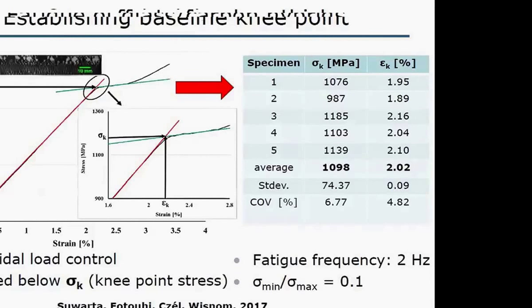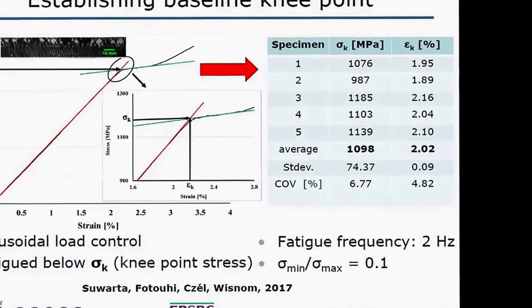This is done under load control, sinusoidal fatigue loading with a 2 Hz frequency and an R ratio of minimum to maximum stress of 0.1. So what we see is that at 80% of that knee point strain, there is no visible change in stiffness or damage up to 100,000 cycles. So this is plotting here the normalized stiffness against cycles, and a number of specimens have been tested, running out to 100,000 cycles at 80% of that knee point stress, with no damage. So that's good, because that says if we're operating at that low point, then we've got no problem with fatigue.